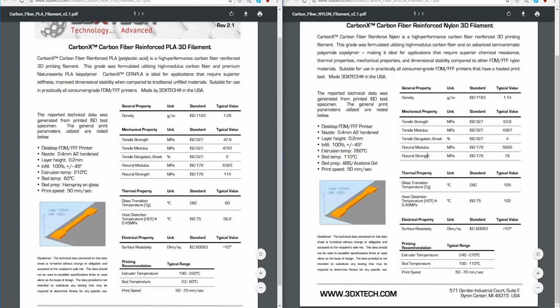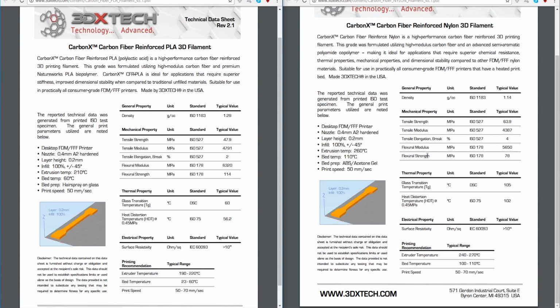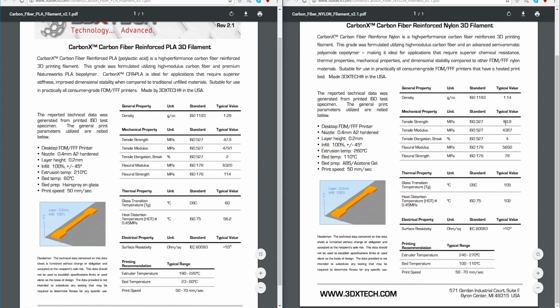And then who knows? Maybe it's even easier to print. And if it's easier to print and it doesn't curl as much, then there's no point in picking the ABS. Nylon beats the ABS hands down. Here though, you have a drop in stiffness, double the elongation, double the flexural modulus. I mean, a little bit. Sorry, this is a little bit under, and this is quite a bit under.